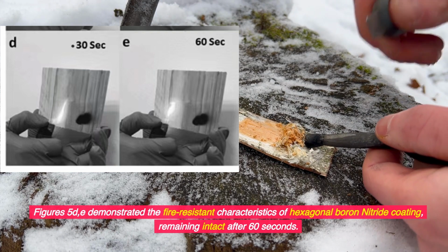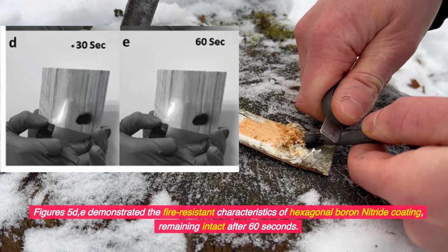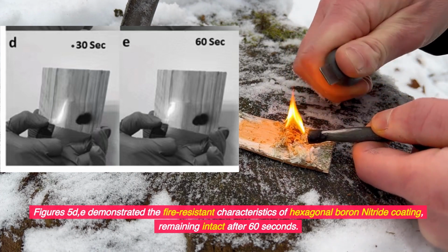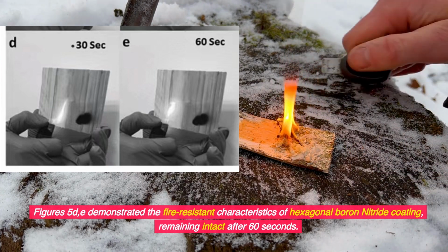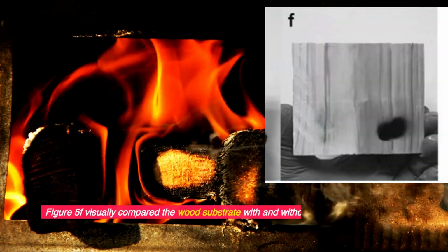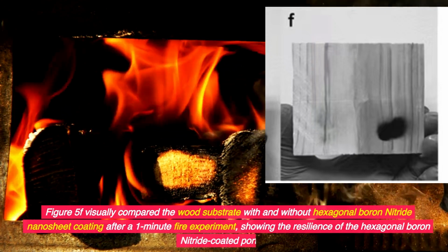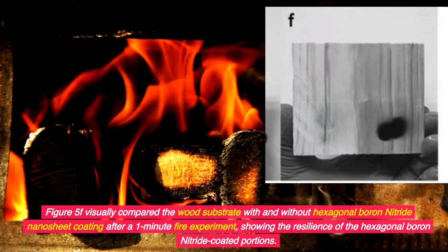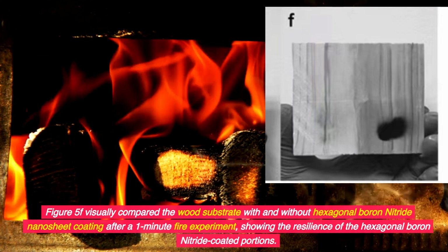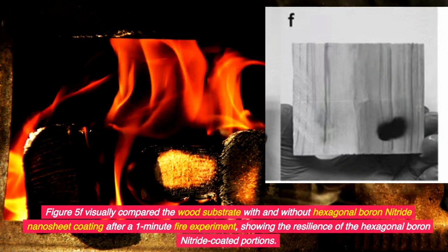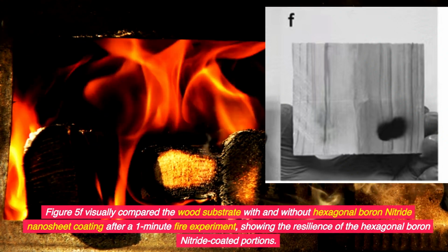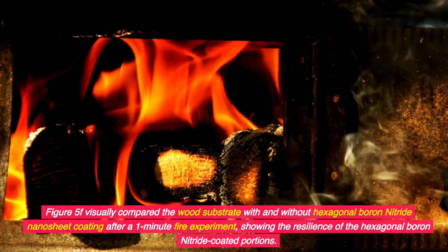Figure 5D demonstrated the fire-resistant characteristics of the hexagonal boron nitride coating, remaining intact after 60 seconds. Figure 5F visually compared the wood substrate with and without hexagonal boron nitride nanosheet coating after a 1-minute fire experiment, showing the resilience of the hexagonal boron nitride-coated portions.